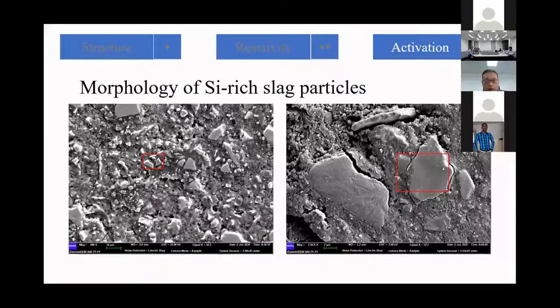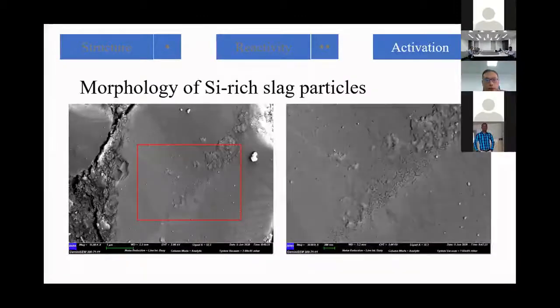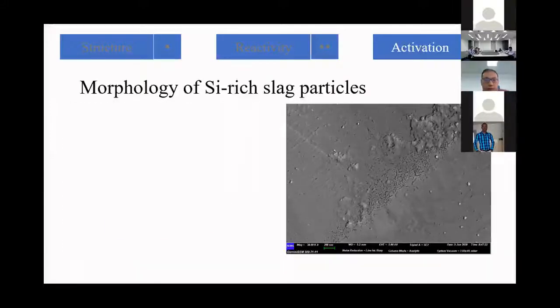And from these high resolution images, we cannot really observe any reaction products. Instead, we see some very typical etch pits, which means the dissolution of the glass phase.